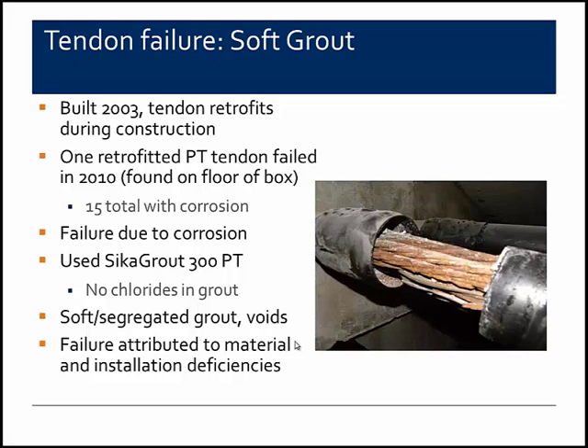The failure they determined or concluded was due to corrosion, and it did use the SikaGrout 300PT, but there were no chlorides in the grout. They did find significant quantities of soft or segregated grout, and they found large voids in the tendons. And so in this case, the failure was attributed not to the chlorides, but to material and installation deficiencies that resulted in both the voids and the soft grout production.